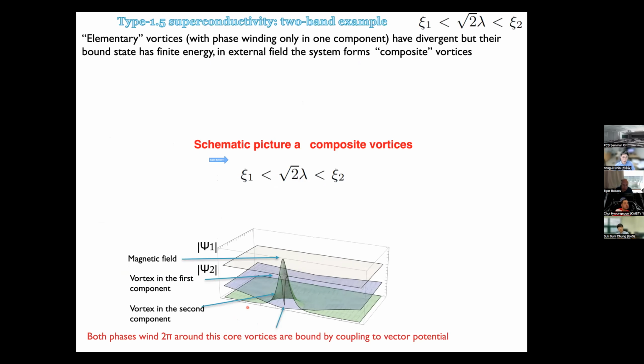Basically, what happens is that in the vortex structure you have 3 length scales. If you apply an external field, the normal external field would produce only integer flux vortices in this material. There are cases where you can produce fractional vortices by external field, but I will not touch on these more complicated cases. In this simplest model, you produce integer flux vortices where 2 fractional vortices are electromagnetically confined, and you have a large vortex core, and another component with a small vortex core. With this type of hierarchy of length scales, the magnetic field is localized in between.